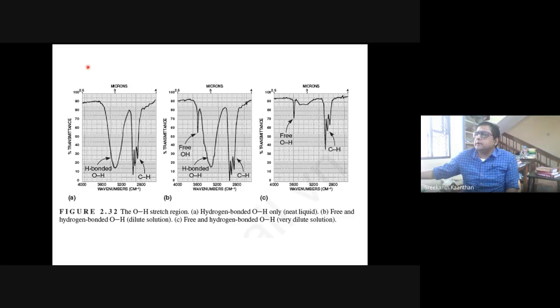What we can see here is different types of hydrogen bonding existing in the system. So in the same molecule, the hydrogen bonded OH is very large. It may look very simple to you, but I think for the people who have really taken IR spectra and observed, if you mess up with your sample, you will get this peak. That means if there is a huge moisture content in the sample, or if your sample is not purified properly, or it is affected by external water, then again you will find such peaks in the spectrum.